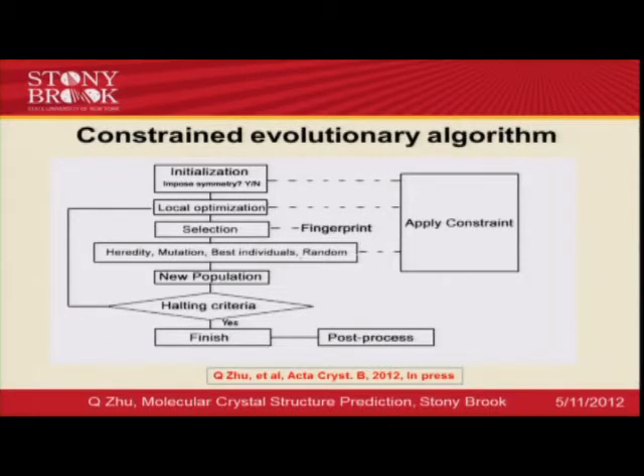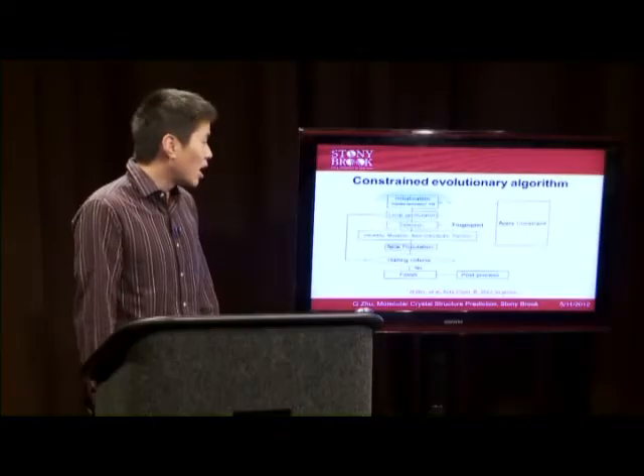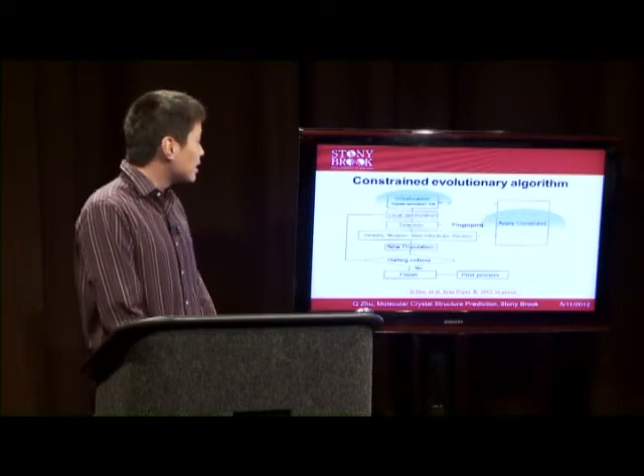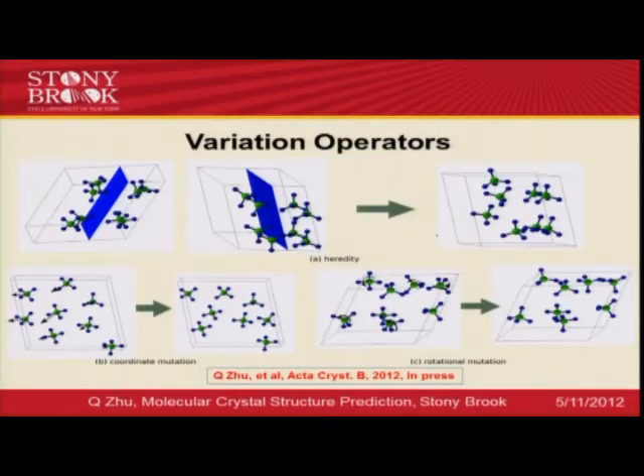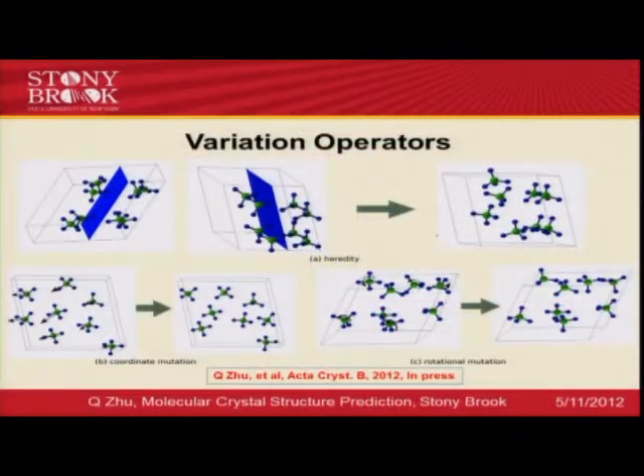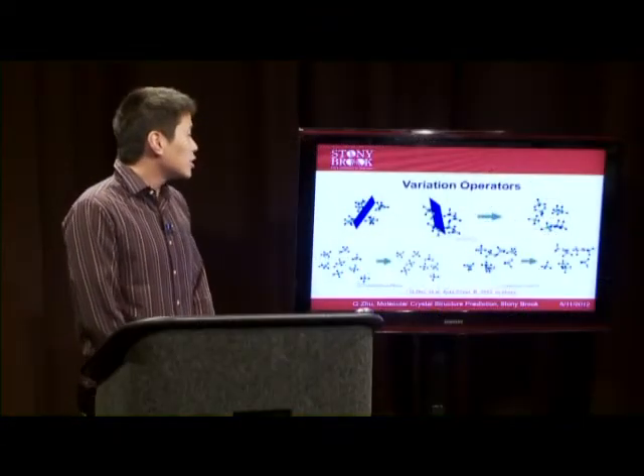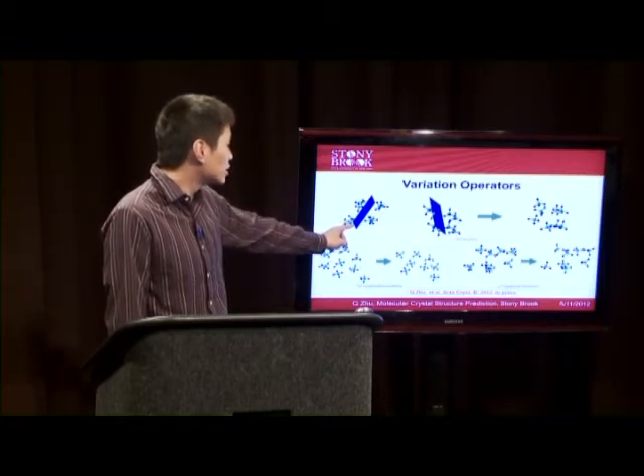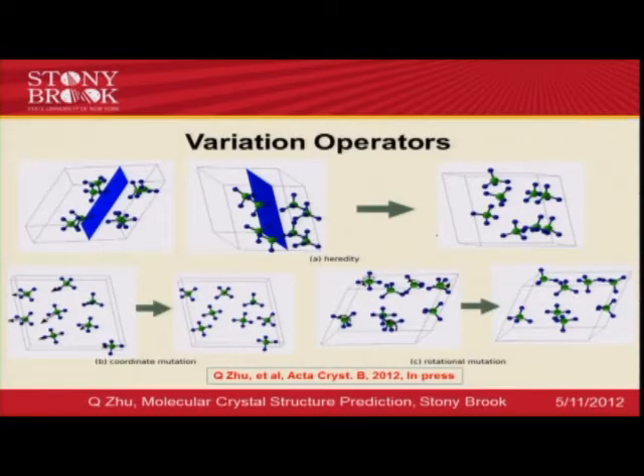For the case of molecular crystals, we made two main adaptations. First, we apply symmetry when generating structures. Second, we apply constraints during the evaluation stage. We have a set of operators to generate new structures from old ones. We can take two selected structures as parents, take one fraction from each, and combine the two fractions to get a new structure. Or we can take one parent structure and mutate the atoms or molecules inside by rotation or translation. Since we apply constraints, molecules are always kept as rigid units so that their geometry is preserved throughout the variation process.